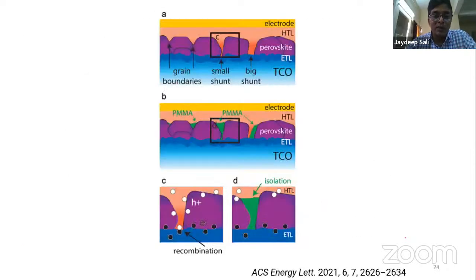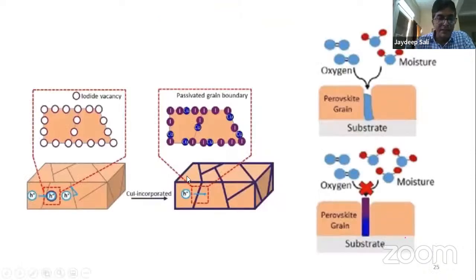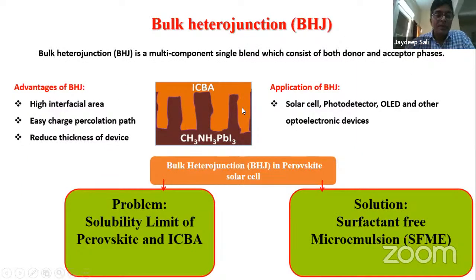So basically, our work is focused on this topic, that is how we can form perovskite thin films with some additives in it. As I have told you, these additives have a function of preventing the penetration, as can be seen in this figure also. These are the lines which represent the grain boundaries. There can be vacancies here, and those can be filled with some other additive, and it can improve the stability.